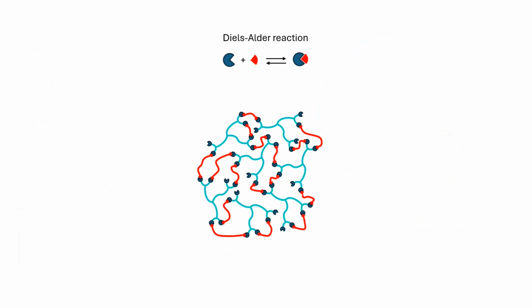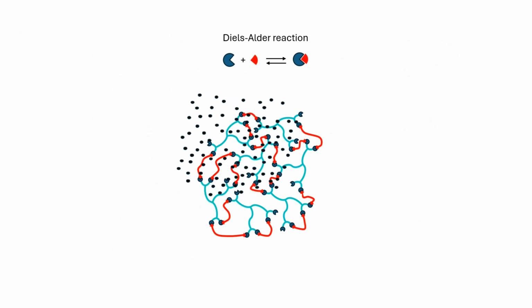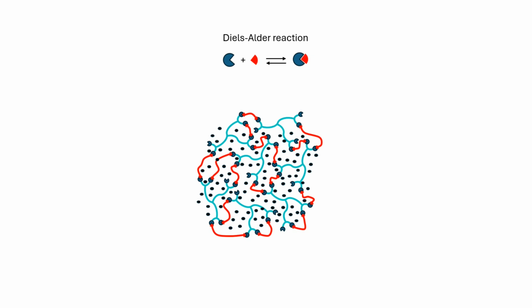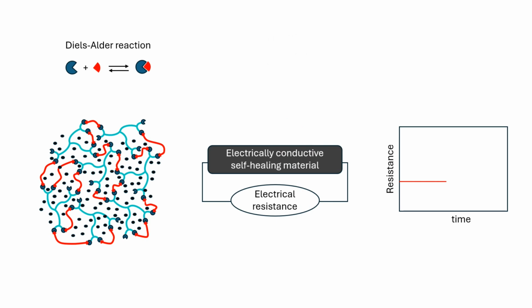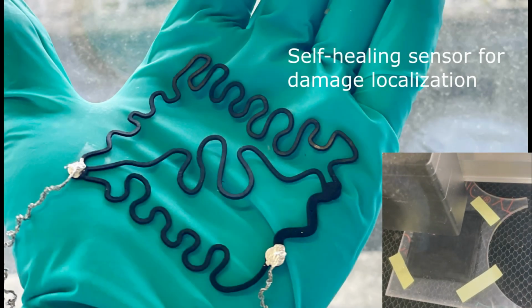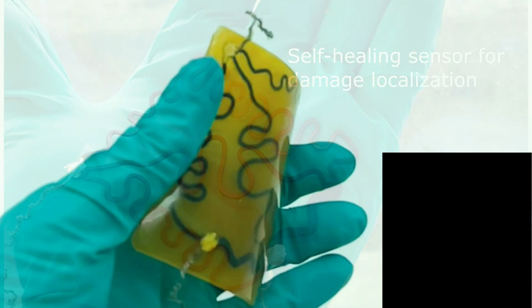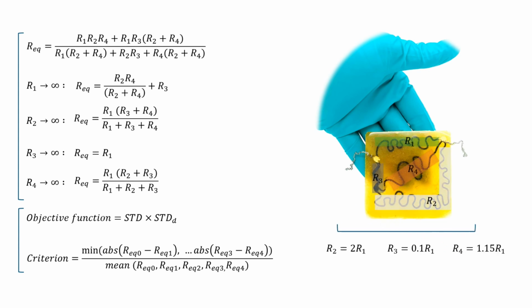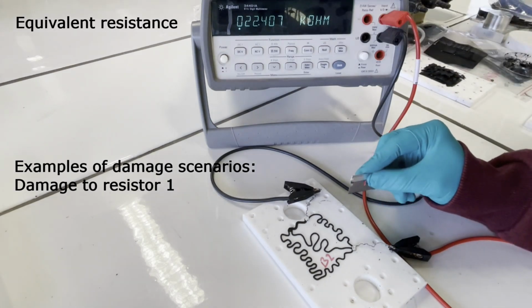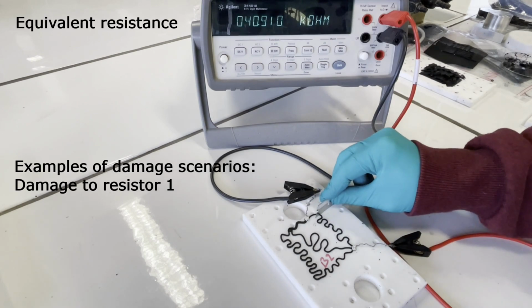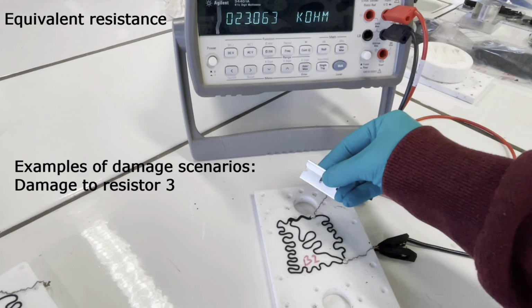They need damage detection sensors. To achieve this, we need to develop a property that can be measured and that changes upon damage. I accomplished this by making the self-healing materials electrically conductive through the addition of carbon black particles. When damage occurs, the conductive pathways are disrupted, increasing electrical resistance, which we can measure. But I aimed for more than just detecting damage. I wanted to localize it to enable targeted self-healing actions. I designed a flexible electronic skin with 4 resistors. By carefully modeling and optimizing the circuit, I found a unique ratio between the 4 resistors, which ensured that each damaged pathway causes a distinct equivalent resistance change, allowing the system to pinpoint the damage at 4 zones with only 2 measuring electrodes.